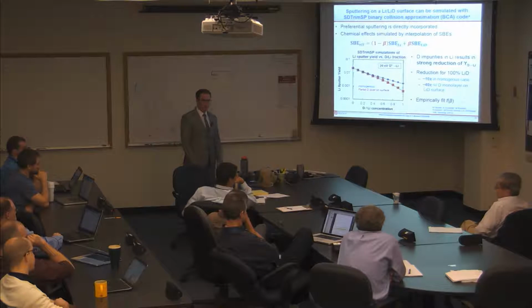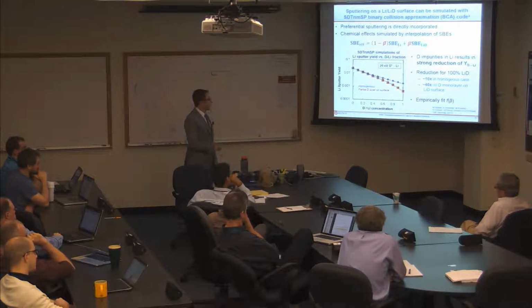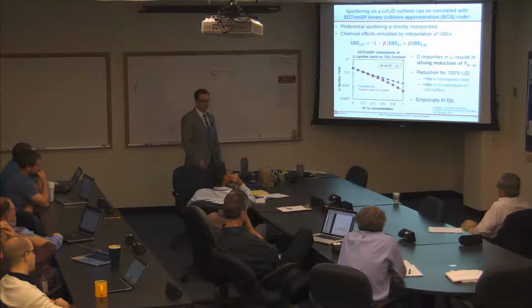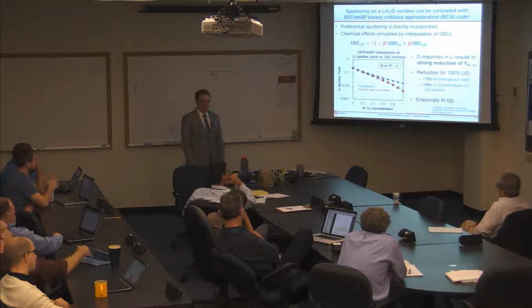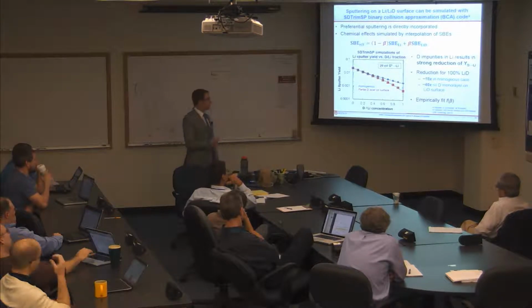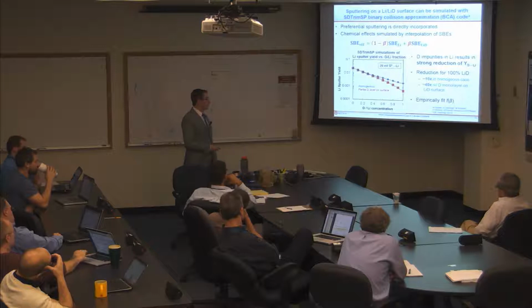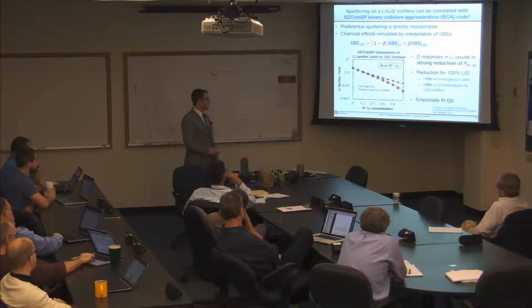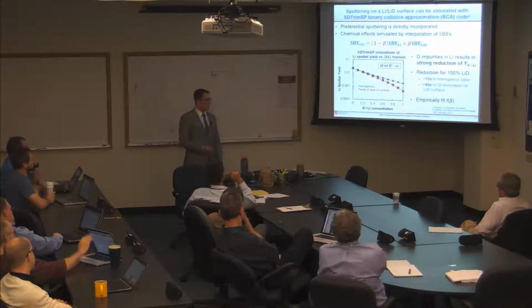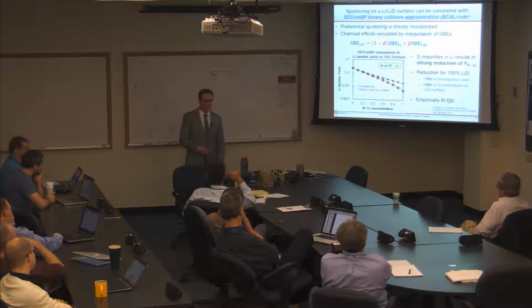Okay, so can you give us a physical feeling for why it's a factor of 10 in the reduction, or a factor of 40? Well, you have to remember that there's also this surface binding energy reduction effect going on. That incorporates an additional reduction into the sputtering yields. And it's not even necessarily linear with the deuterium to lithium concentration, because the deuterium atoms are sputtered a lot more efficiently than lithium atoms by deuterium ions.